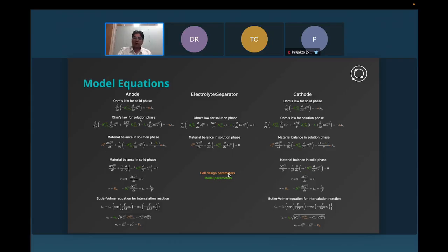Now, for all of these processes, one needs to know what the diffusivity is through each of these particles, cathode or anode. What is the diffusivity in the electrolyte? What are the reaction rates once the lithium ion converts into lithium by combining with the electrons? Or what is the reaction rate when lithium decomposes into lithium ion and electrons? All of these parameters play an important role in describing the cell dynamics, and hence accurate estimation of these parameters is very important to understand what kind of response you would expect from the cell when the cell undergoes the charge and discharge process.